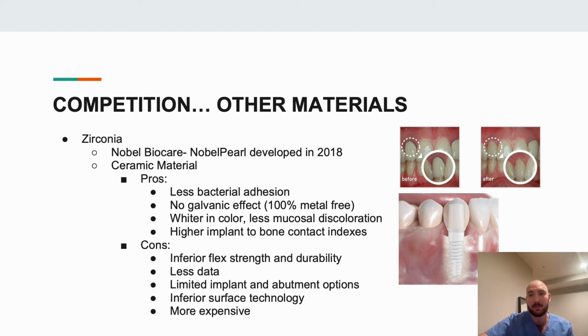However, zirconia implants do have their own set of drawbacks. Zirconia has high compressive strength, but it's more brittle and therefore more prone to fracture under forces that cause bending or flexing. And it's also just a newer material. There's a lot less data to support its long-term success in patients compared to the tried and true titanium implant. And because it's new, there are a lot fewer options with abutments with zirconia-based implants.